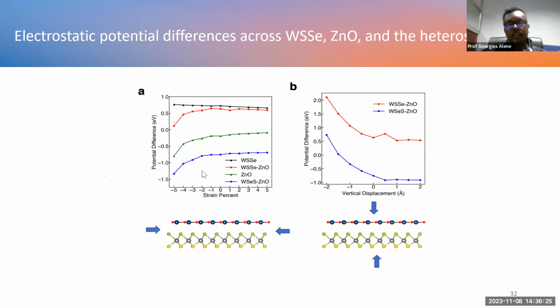So what we have learned is the dipole moment is controlled by the zinc oxide. When I discussed before, I said the zinc oxide has no significant effect on the band edge and the band gap value, that means the electronic property. But when we consider the dipole moment, it is actually manipulated by the zinc oxide. So this zinc oxide has this contribution on this system, on the heterostructure.